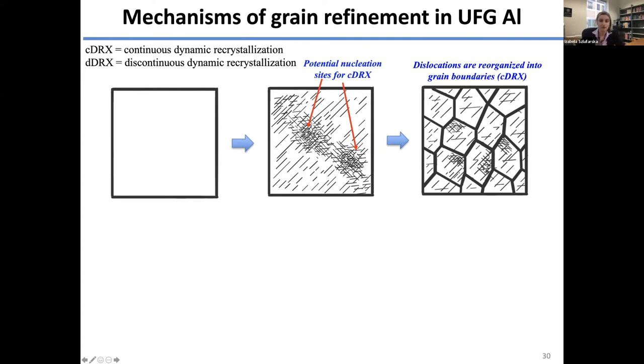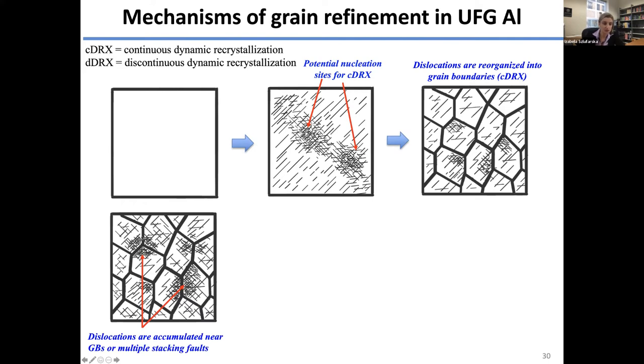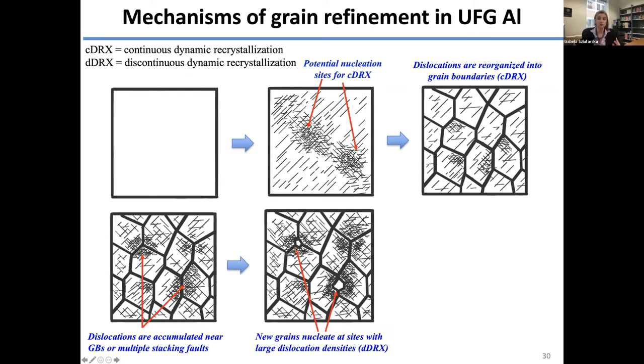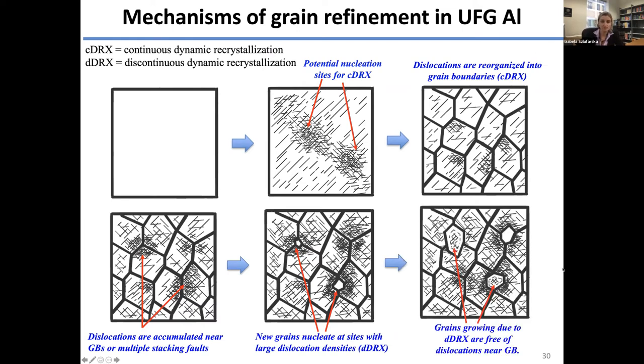Now, further deformation leads to dislocation accumulation near the grain boundaries. Now, the region with high dislocation density has high energy and can become sites for nucleation of new grains that are defect-free. So it's basically a new crystal that nucleates there. Now these grains grow. Initially, they are defect-free, and eventually, further deformation is going to introduce new dislocations inside of the grain. So this process is called discontinuous dynamic recrystallization, and the grains here have a characteristic appearance of being fairly defect-free near the grain boundaries and having higher dislocation densities inside.